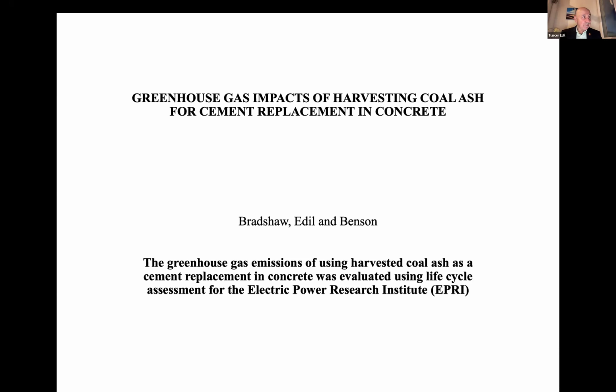And so as a result, there is also concern about the old materials that were disposed, especially in impoundments. And you know what happened in Tennessee, a fly ash impoundment broke and caused a lot of environmental damage. So EPA doesn't want these impoundments anymore. They need to be removed. And so what do you do? You harvest this material, and there are two options. You either put it in a landfill, or you beneficiate and use it in construction.